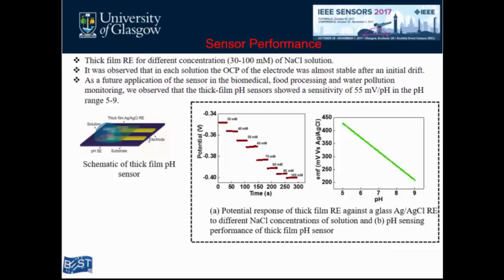I didn't show here this work in different solutions, different interfering ions, selectivity issues; all of that we characterized for this pH sensor. And another characterization I did is that here you can see, with different NaCl concentration solutions, the performance of this device with a stable potential. You can observe here a stable potential of this thick film against this thick film reference electrode. We can miniaturize it again. Now the active area is almost 1.5 centimeter square, and we recently did 0.5 centimeter square also.